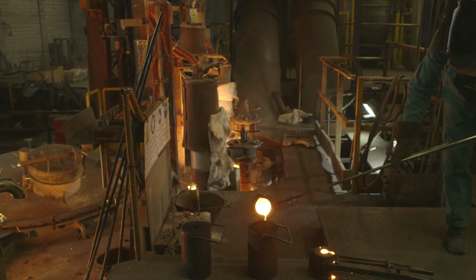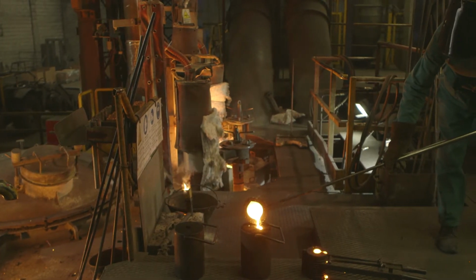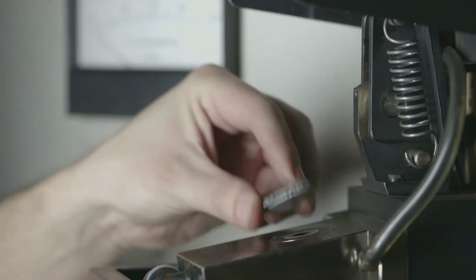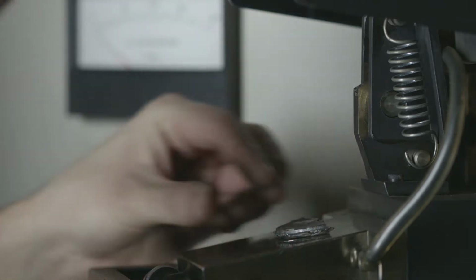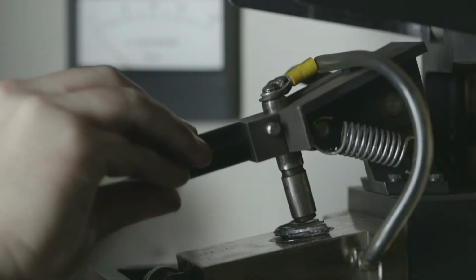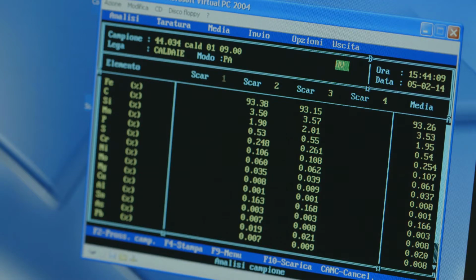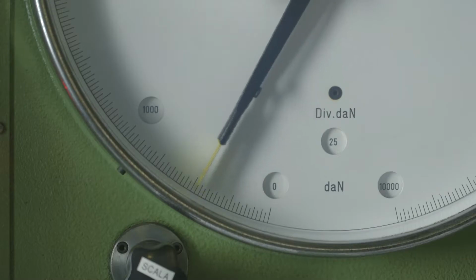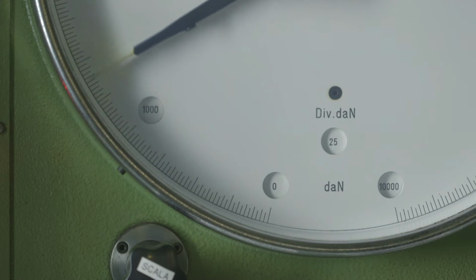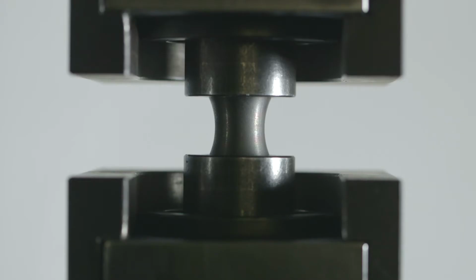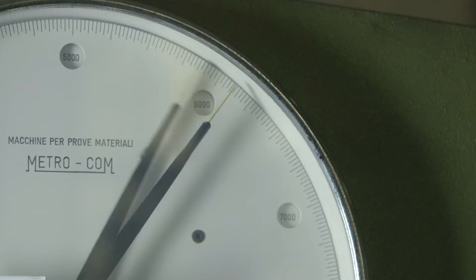The cast iron is tested twice every hour using the carbon equivalent test. Every 2 hours, the technology lab draws samples to run strict chemical analyses with a mass quantometer. Every 4 hours, a mechanical traction test is run to measure the quality of the produced cast iron with certainty.